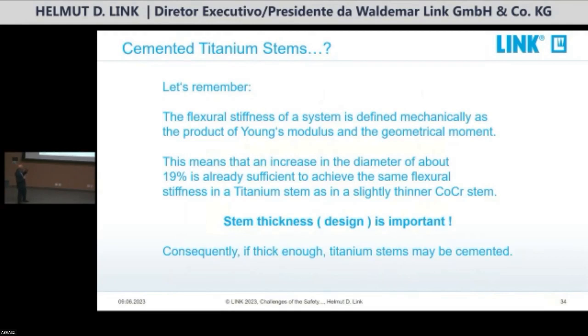This means that an increase in diameter of about 19% is already sufficient to achieve the same flexural stiffness in a titanium stem as in a slightly thinner cobalt chromium stem. Stem thickness is important. This is also very important to tell the surgeon. There are always surgeons, some surgeons had a bad breakfast maybe.